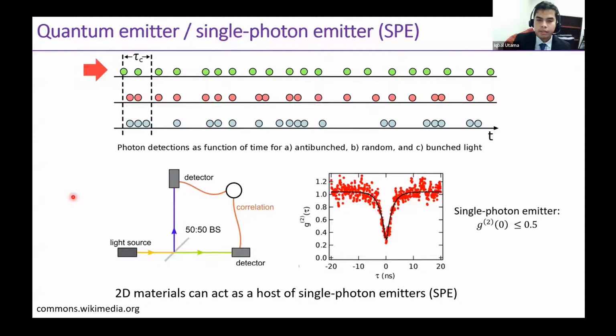The experimental technique that has become the gold standard to verify this photon statistics, and whether you really have single photon emitters, is the so-called Hanbury Brown and Twiss setup, as shown over here, where the light is passed through a 50-50 beam splitter towards two separate detectors, and the light detected is then correlated in time to form the so-called second order correlation function as a function of time delay, being the time that has elapsed after or before which a photon arrived onto one of the detectors.